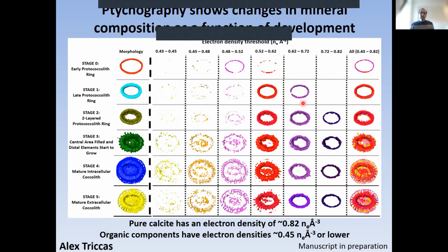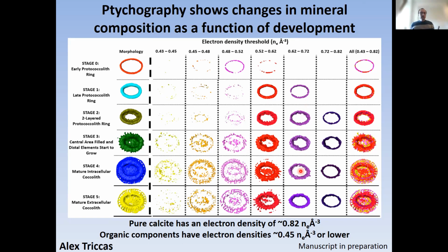And that is indicating that the remaining of the structure, the outer layers, if you will, is either, again, containing high amounts of organic, or maybe it's a porous structure. That is something that we're still working out how to explain exactly. But there is something really interesting and really thought-provoking that's happening here. But the point here is that they are made of calcite. Each strut is a single crystal of calcite, but maybe this is not really pure calcite. There is something else in there that is contributing to this very low electron density.